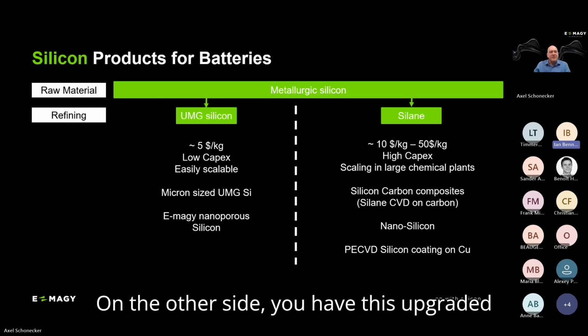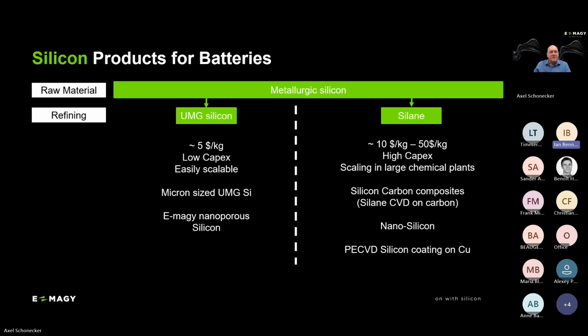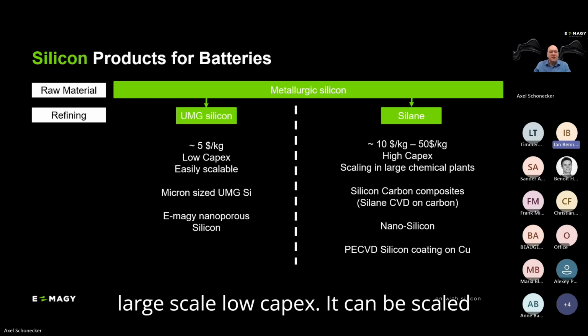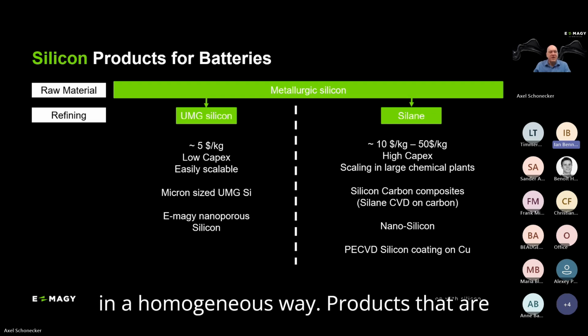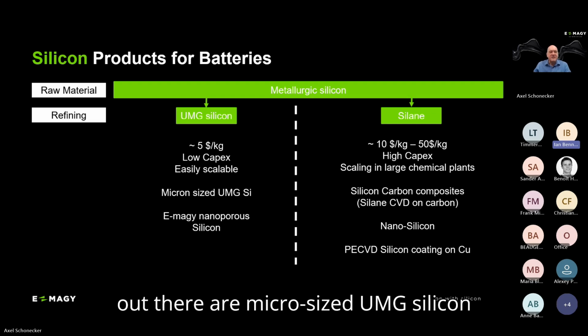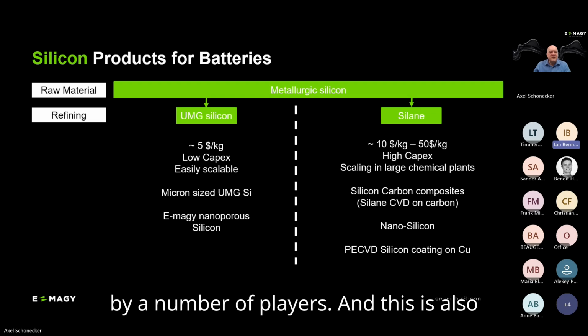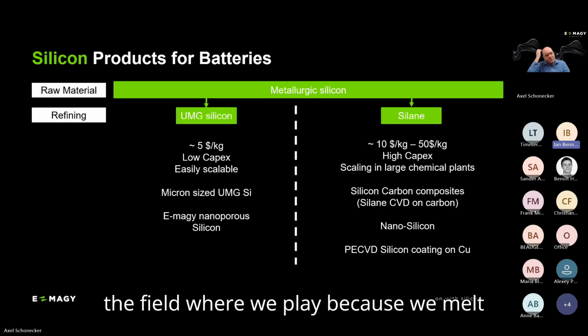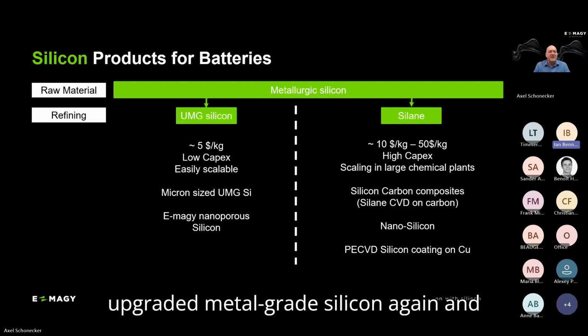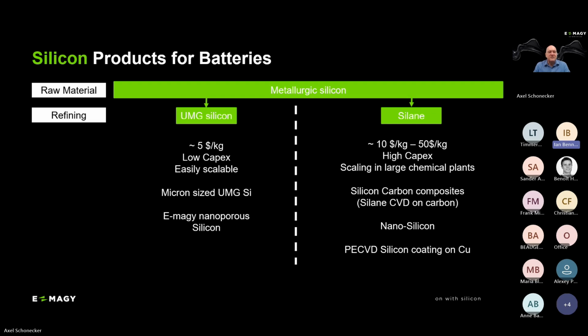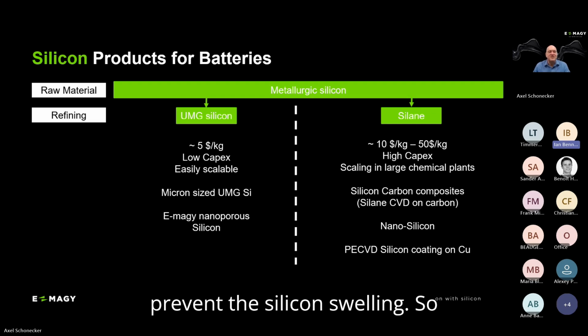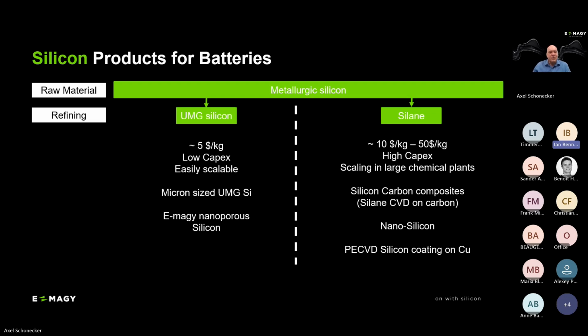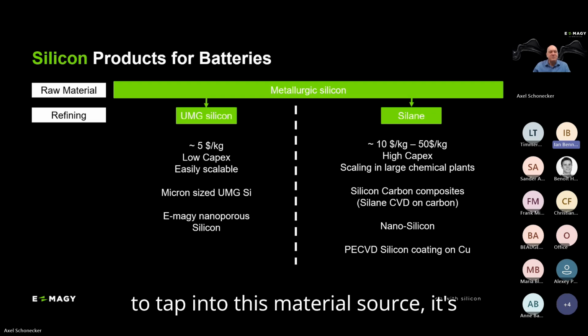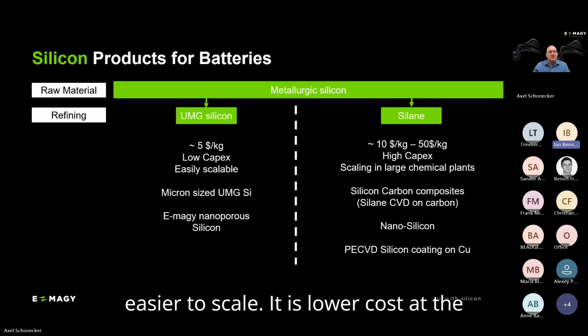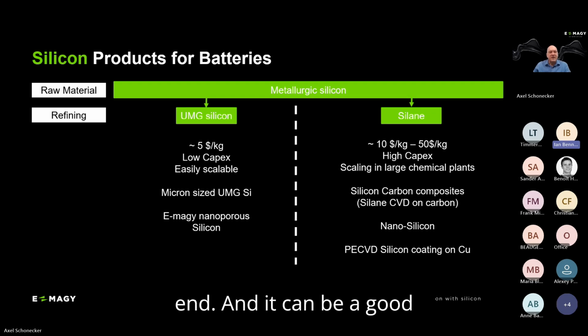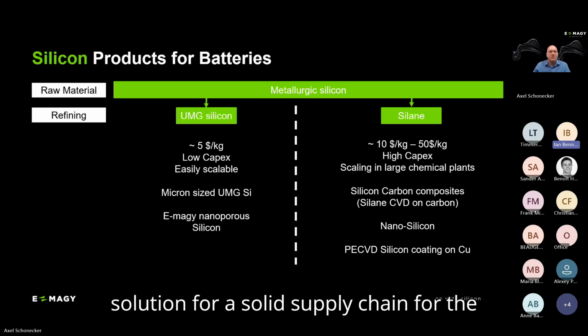On the other side, you have this upgraded metallurgical grade silicon. The cost for that is relatively low on large scale, low capex. It can be scaled in a homogeneous way. Products that are out there are micro-sized flake silicon by a number of players. And this is also the field where we play, because we melt upgraded metallurgical grade silicon again and let it crystallize in this nanoporous silicon structure that is helpful to prevent the silicon swelling. So we think if you're able to tap into this material source, it's easier to scale. It is lower cost at the end. And it can be a good solution for a solid supply chain for the battery industry.